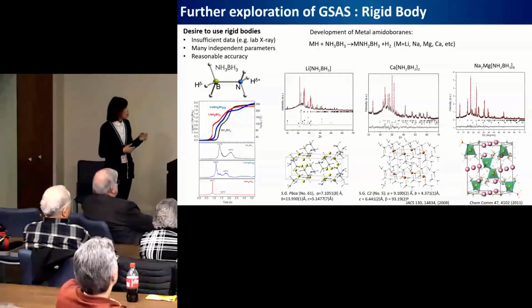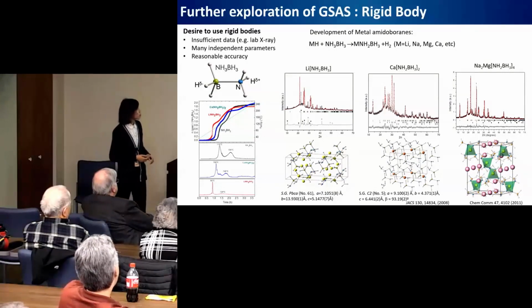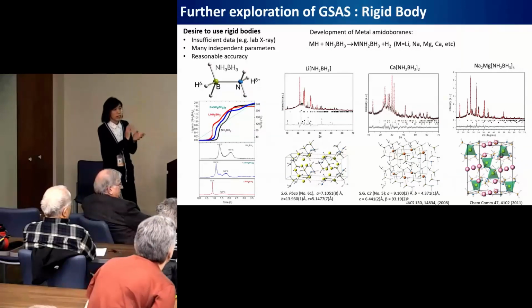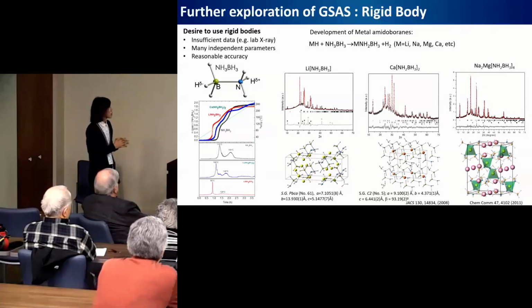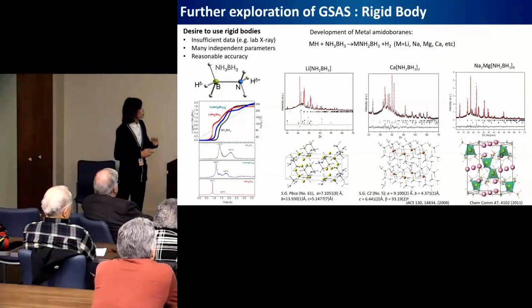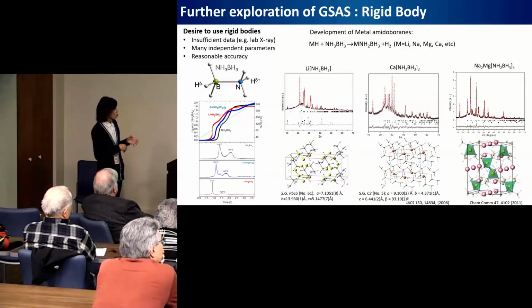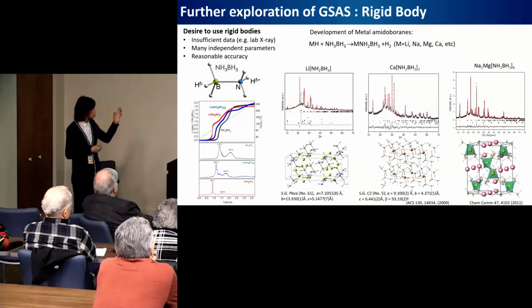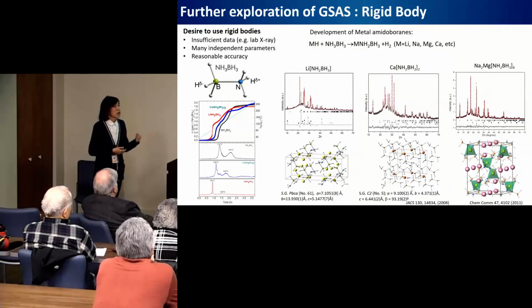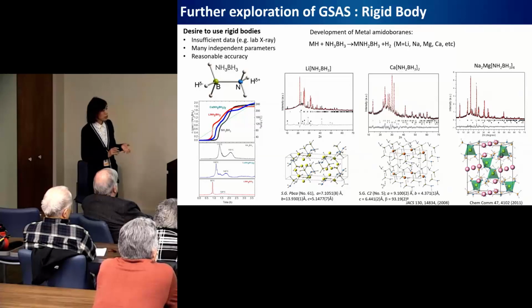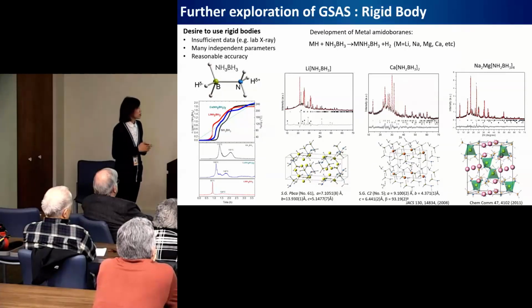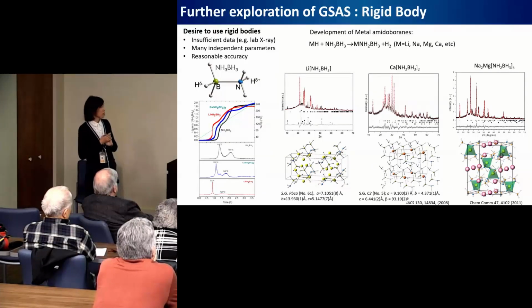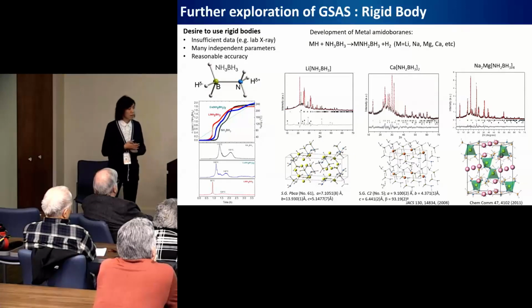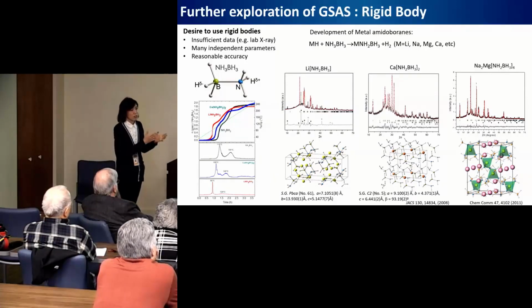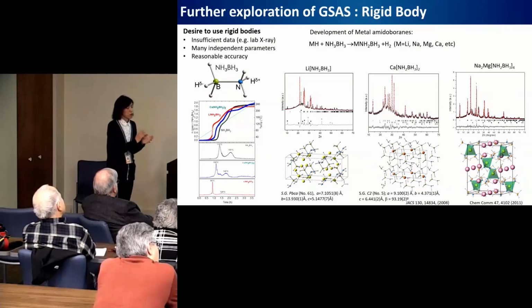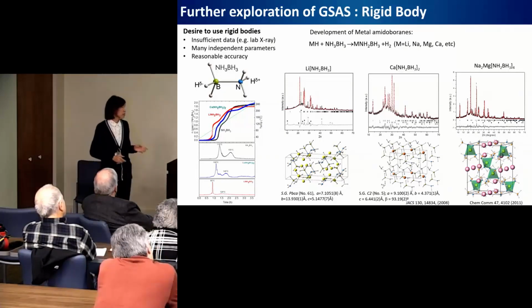unwanted gases. So then we developed these metal amidoborane compounds by reacting metal hydrides with ammonia borane. These compounds show greatly improved dehydrogenation properties compared to ammonia borane, in terms of accelerated kinetics, reduced dehydrogenation temperature, and suppressed or minimized impurity gases. And interestingly, they all have very fascinating crystal structures. So we were able to determine the structure based on powder X-ray diffraction data.